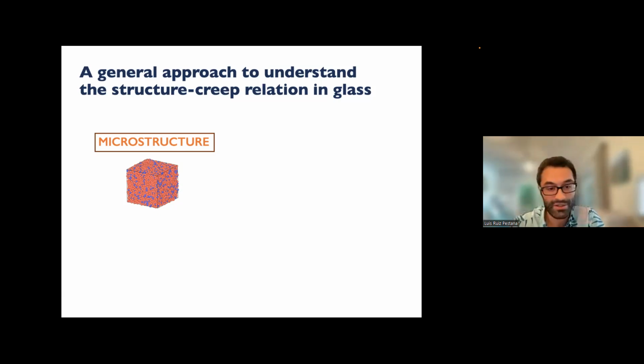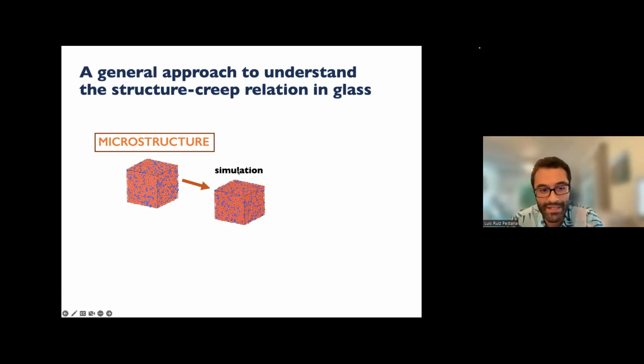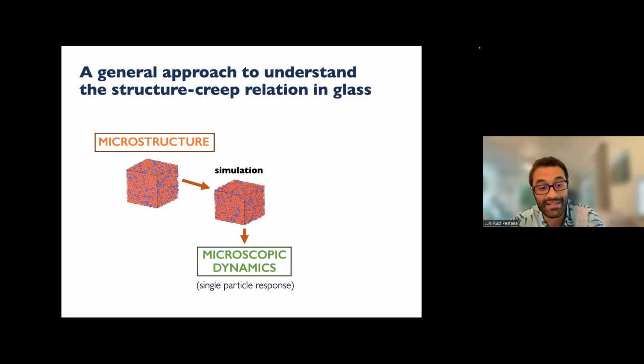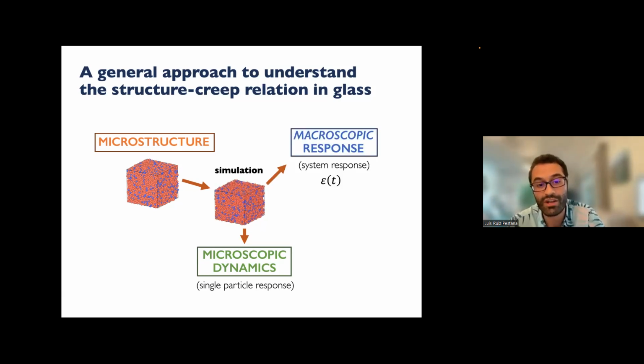So you have a microstructure. What does that mean? You have a bunch of atoms or colloids in a box forming a glass in a disordered structure. You can run a simulation. In our case, we use molecular dynamics simulations, and these are either atoms or colloidal particles, like nanoscale stuff. But again, you could use other simulations and simulate the formation of a granular system. So from the simulation, what do you get out? Well, you get access to microscopic dynamics, by which I mean the single particle response. And you also get access to the macroscopic response.